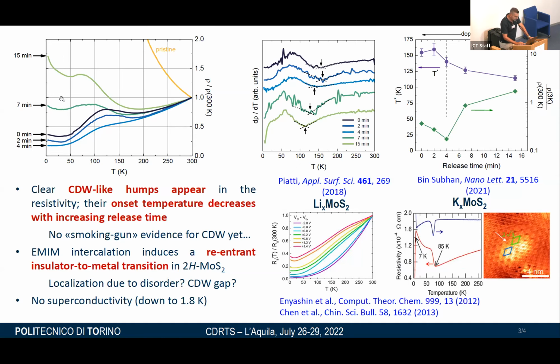So first of all, we see these humps that are suggestive of the existence of a charge density wave order. And indeed, if we plot the derivative of the resistivity as a function of temperature, we can extract the temperature of formation of this charge density wave, which is increasing with doping. And moreover, there is a sort of decrease first and then increase again of the low temperature resistivity, which is suggestive of a sort of re-entrant metal to insulator transition. What are the possible causes of these two behaviors will be discussed in front of the poster.